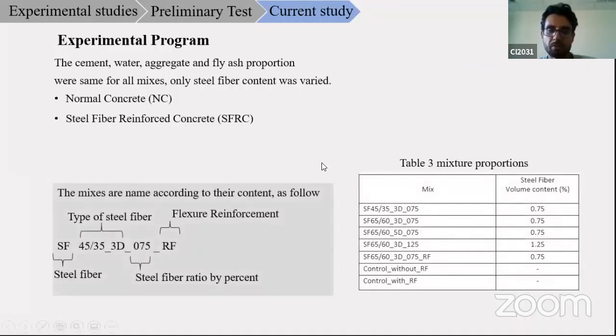Here, the mixtures are named according to their content as follows. SF represents the steel fiber, then the type of steel fiber, and the steel fiber ratio by percentage. Two specimens were cast with normal concrete without steel fiber, and one specimen was cast with reinforcement with steel fiber volume content of 0.75, and one with the fiber volume of 1.25%, and the other was cast with 0.75%.